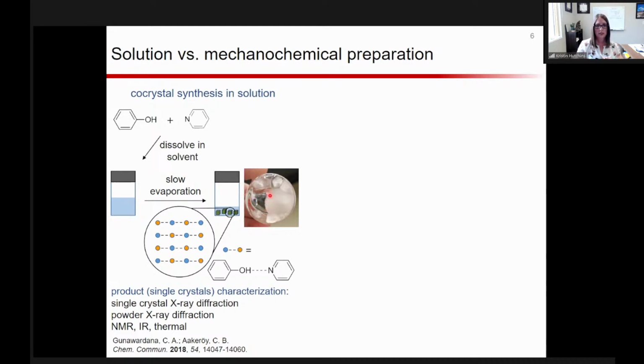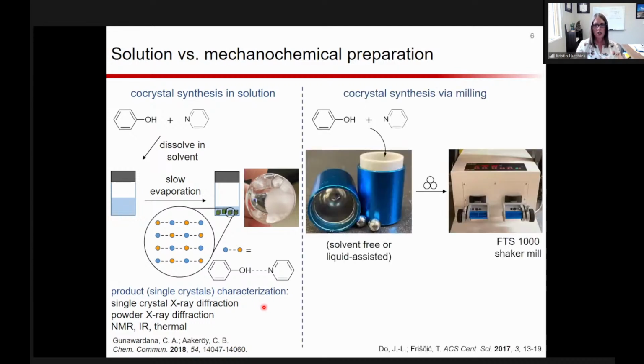But then if you have large enough single crystals, you can actually pull one of those out and do single crystal X-ray diffraction to look at the structure. And then you could scoop out the bulk material and do powder X-ray diffraction to confirm that the single crystal you pulled out actually matches this bulk material, and you didn't just pull out one crystal that happened to be good. So powder gives you a bulk idea. You can also do spectroscopy, NMR, and IR to confirm that both components are present, and you'll also typically see some shifting of peaks if they're actually co-crystallized. And then you can look at thermal properties as well. Again, thermal properties are going to tell you a co-crystal versus things like a physical mixture of the 2.